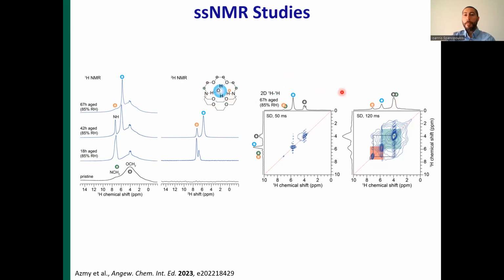In order to elucidate local interactions below 5 angstrom, we performed 2D proton-proton NMR studies, where after 50 milliseconds, we were not able to record a signal corresponding to interaction of the different types of protons. However, after 120 milliseconds, we record a much better signal where we could clearly observe the interaction at close proximities below 5 angstrom of the protons of water and the protons of the cryptand ligand, which verified that the water molecules are in very close proximity with the cryptand ligand.